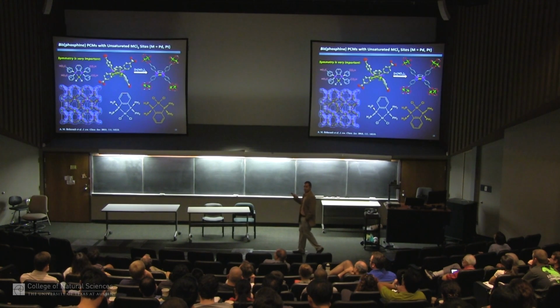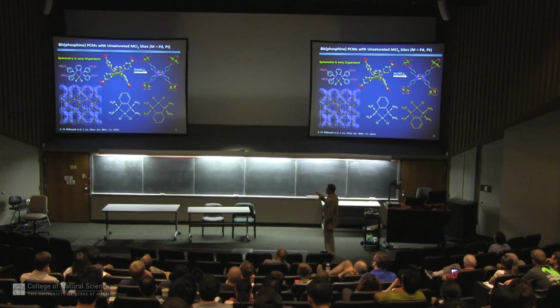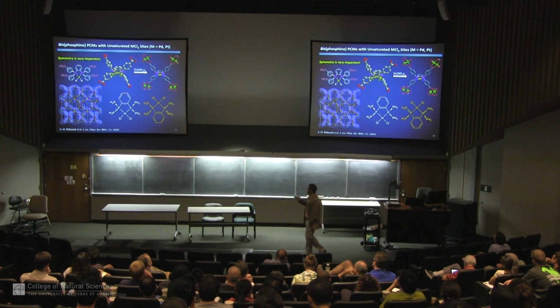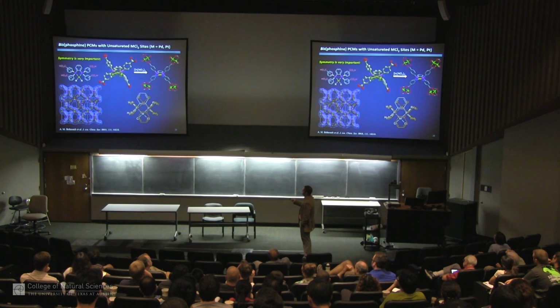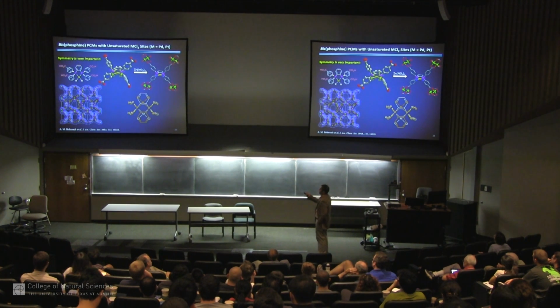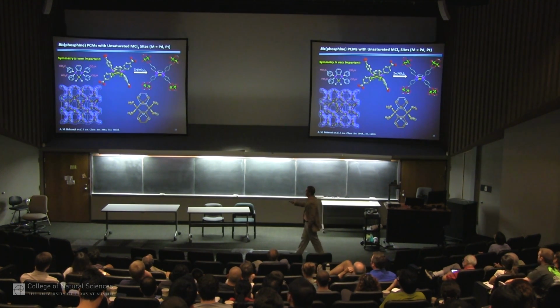I don't know whether Vince Lynch is in the room, but Vince has discovered that the crystallography of these is very difficult, and we've struggled in many cases because the symmetry is so high that these things all do this in the framework. They can insert themselves in one of two directions. And so really this is completely disordered. The symmetry here is so high that these are back to front at random positions.